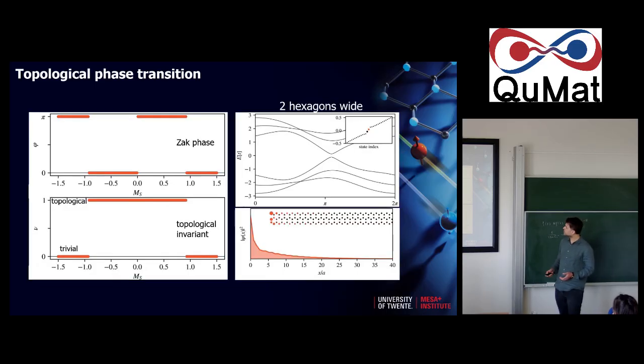In a bit wider nanoribbon, also topological, you see that the state is really localized at the end in the calculations. And if you calculate the exact phase and then extract the topological invariant, you see this phase diagram for the topological invariant over staggered mass. Staggered mass is the vacuum that we have in the system, this staggered potential. You see that over a wide range of staggered masses for this 2 hexagon wide nanoribbon, you have a topological invariant of 1, which means that it's a topological system. And if you exceed that range, then you go to 0, which means it's trivial.